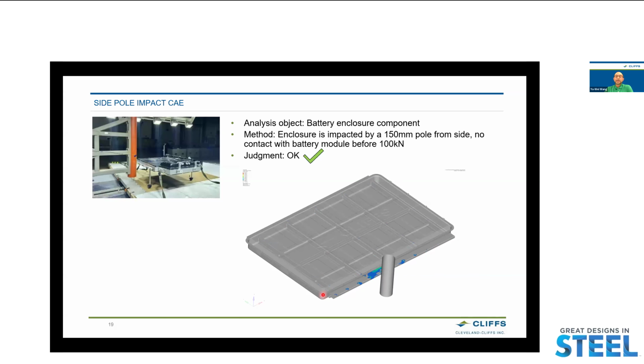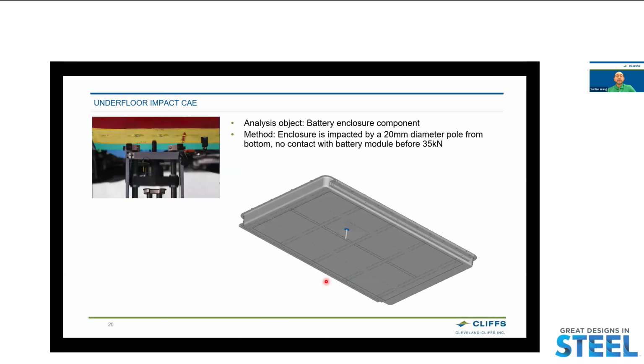So there's no touch to the battery, meeting our target of no touching to the battery module before the load reaches 100 kilonewton. And this one shows the setup for the CAE model to simulate the underfloor impact. As you can see, the 20 millimeter diameter pole is placed at the weakest location. This is between the two cross members, as well as the longitudinal cross member and the longitudinal stiffener. So this is in the middle of nowhere.